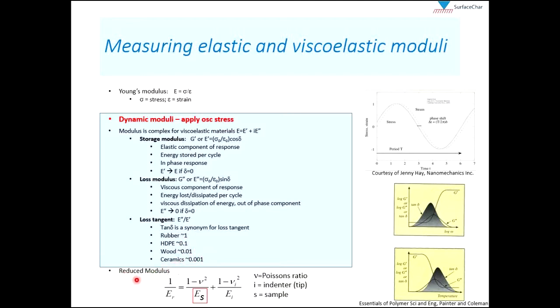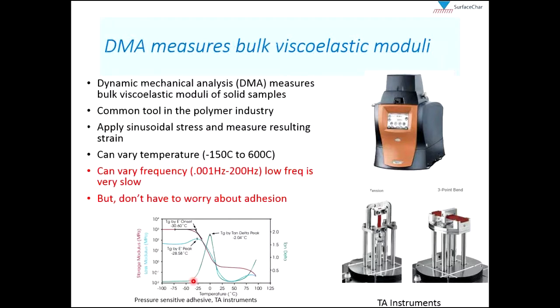Now there's a final modulus called a reduced modulus, and the reduced modulus is actually the parameter that we always measure in AFM, and that's simply the combined tip and sample properties. So this is what we measure, and then we're able to extract out the sample modulus. Now in the bulk, we use dynamic mechanical analysis, or DMA, to measure viscoelastic moduli of solid samples. This is a very common tool in the polymer industry, and here's just an example of a DMA from TA Instruments. And again, it works by applying a sinusoidal stress and measuring the resulting strain.